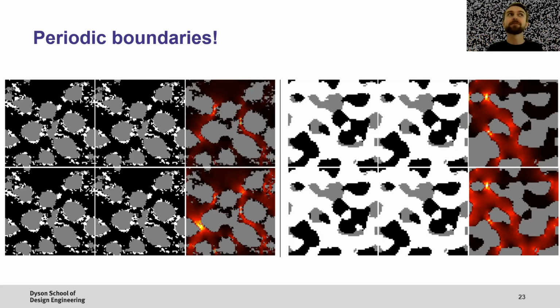But that can have really devastating consequences for the representativity of your sample, because you end up chopping off small fragments of particles on the side. And as far as that mirror boundary is concerned, that is now just a very small shard particle. So your particle that you had a nice tomography of in all this central region, now at the edges of your volume, you've got these very strange, unrepresentative shapes. And that will mess with the results, right? That will suggest that your battery might charge much faster than it would in reality.